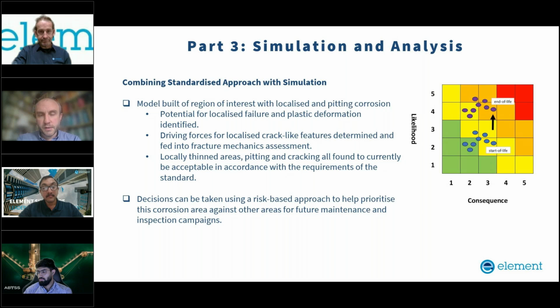And on the right here, this is not the actual case that we had in the project. I couldn't share that, unfortunately, for sensitivity reasons, but there were areas of damage that were able to demonstrate that they were sitting in the more benign region of a risk matrix at the point at which they were found. So they had a very low likelihood of causing a failure. As time progressed over the next 10 years, we were able to demonstrate that they were actually creeping into slightly higher severity regions of the risk matrix in terms of the likelihood of failure.